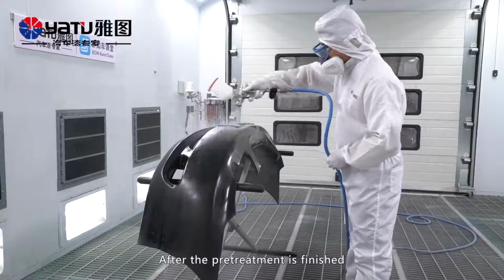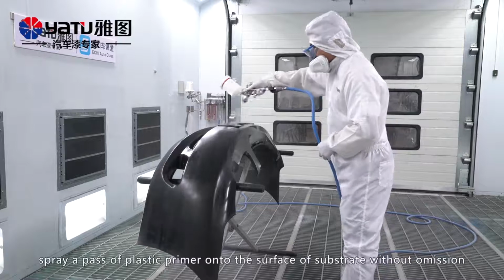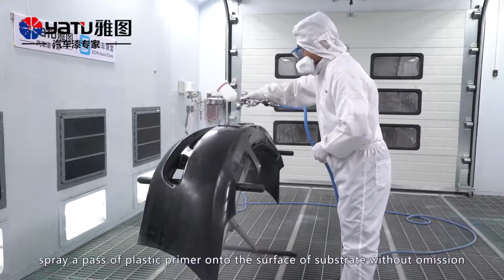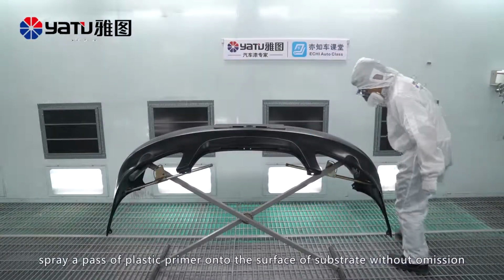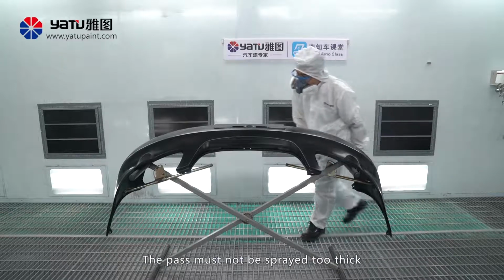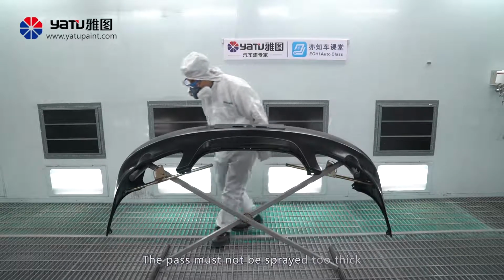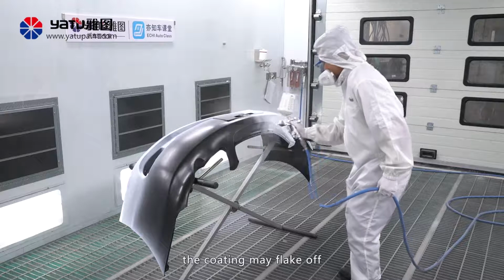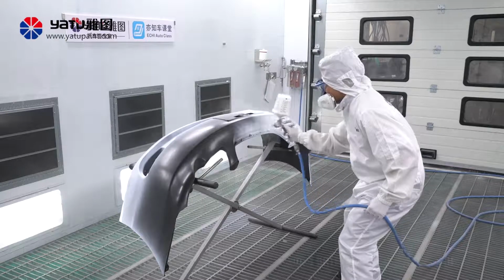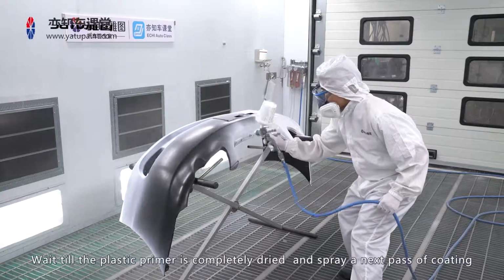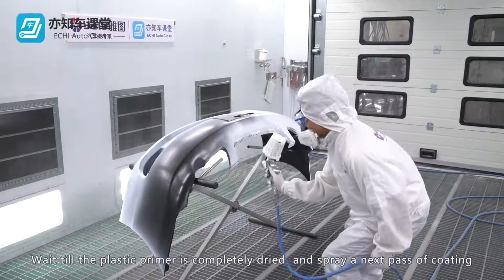After the pre-treatment is finished, spray a pass of plastic primer onto the surface of the substrate without omission. The pass must not be sprayed too thick, otherwise the coating may flake off. Wait till the plastic primer is completely dried and spray the next pass of coating.